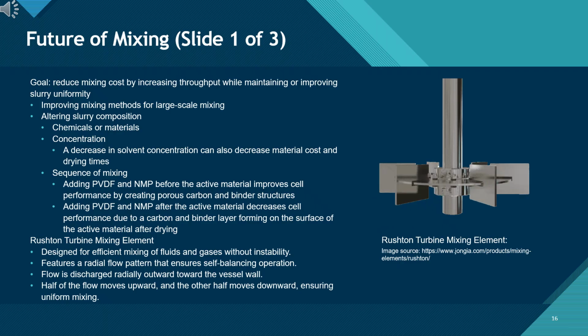Adding PVDF and NMP before the active material supports better porous binder-carbon structures, whereas adding them afterward can reduce cell performance. The animation shows a Rushton turbine, a radial flow impeller that provides stable, balanced mixing. It pushes fluid outward and circulates flow both upward and downward, enabling uniform dispersion, critical for consistent battery slurry quality.